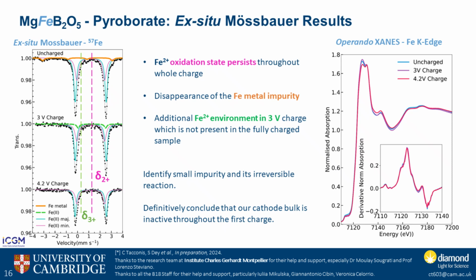We went to do some ex-situ to figure out really if there was any iron redox going on in our material. There's a lot going on here, so I'm going to guide you through it. So the first thing is the center of the 2 doublets is not changing. It's not shifting down to lower values. So we're actually, unfortunately, not changing our iron redox. Again, as a reminder, if we were seeing any sort of iron 3+, we would at least see some doublets shifted with a center at around 0.4, which we don't see. So the iron 2+ oxidation state persists throughout the whole charge.